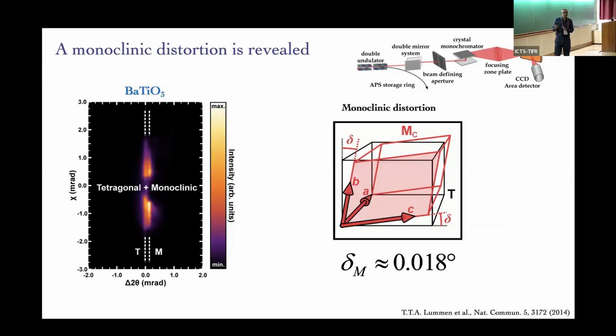But you should not always rely on optics because we don't have the resolution. Plus, we are doing all this modeling too, you know, sometimes you can fit an elephant if you have enough equations. So you have to be very careful. X-ray is always a good thing. So this is an X-ray beamline, which is called the hard X-ray nanoprobe at Argonne National Labs. They can take X-rays and, using Fresnel zone plates, focus them down to 30 nanometers. X-rays are very hard to focus because they don't interact with the material. But they can do that with these Fresnel zone plates.